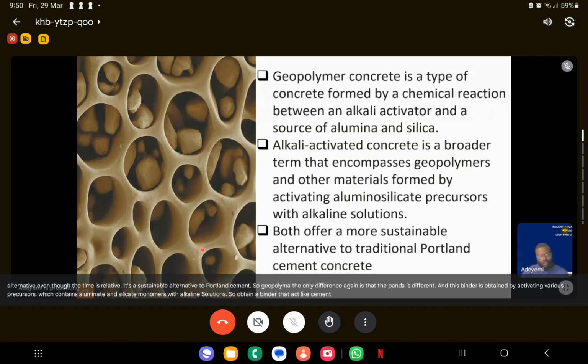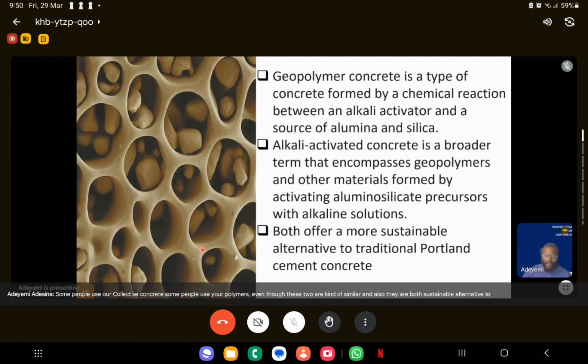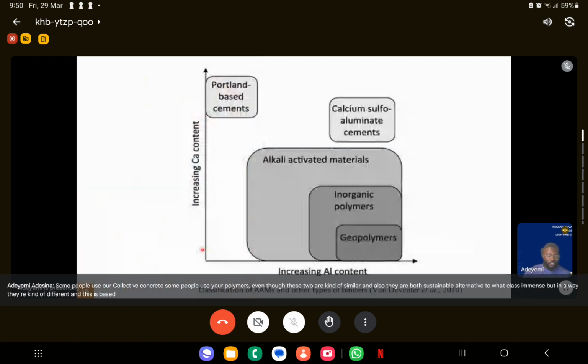And there's really a lot of confusion in this field right now. Some people use alkali activated concrete, some people use geopolymers. Even though these two are similar and both are sustainable alternatives to Portland cement, in a way they are different, and this is based on the chemical composition. So again, I'm putting up this very common figure, which I found really helpful, that separates different kinds of binders. You can see this is based on the amount of calcium and the amount of aluminate monomer you have. Portland cement is very high in calcium, which is responsible for a lot of the high strength we achieve, because when you have your hydration reaction, that forms your calcium silicate hydrate, your calcium hydroxide, the heat, and so on.